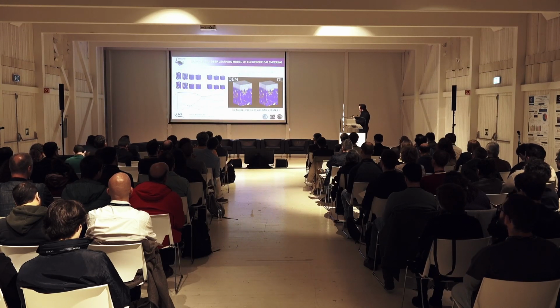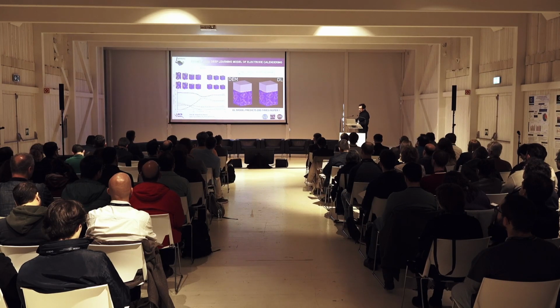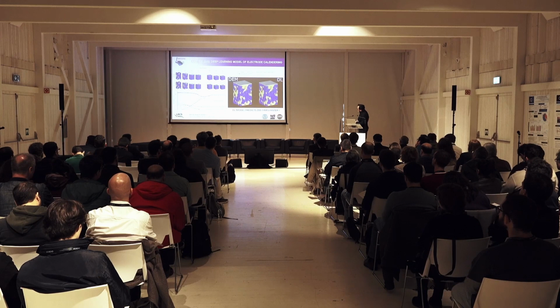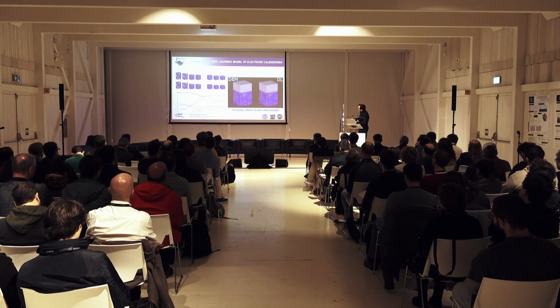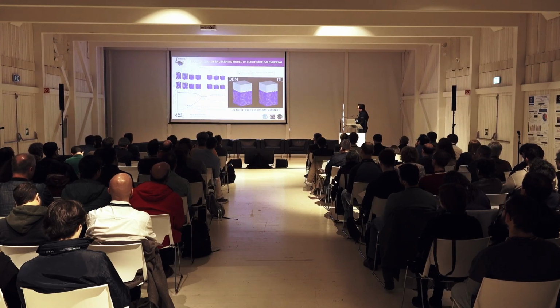And here you see a comparison between the deep learning prediction and the discrete element simulation prediction of this calendering process step. You see a very good agreement in the time series for the volume occupied by the active material, the carbon binder domain, the void, which is all the space on top of the electrode being compressed, and the pores inside the electrodes. So I will speak about accuracy here. Accuracy is something like 95%, okay, in terms of this time series prediction.